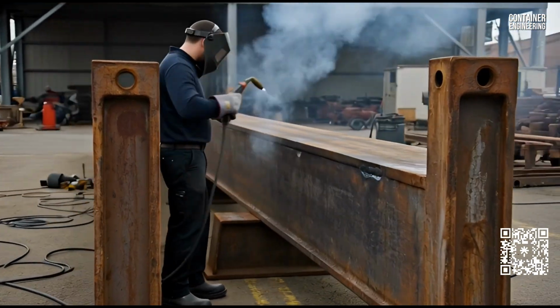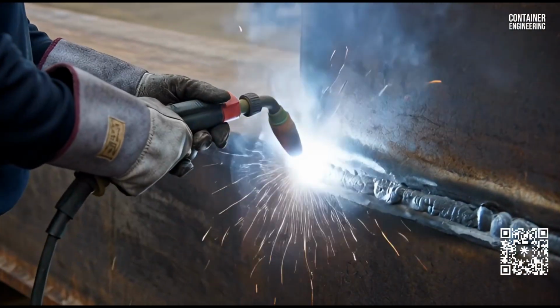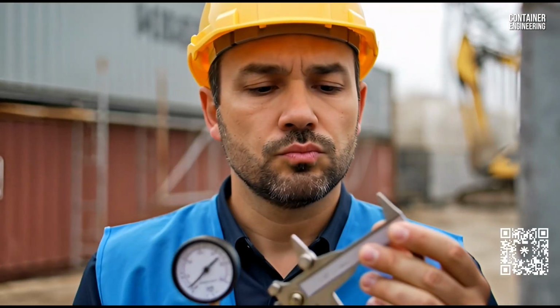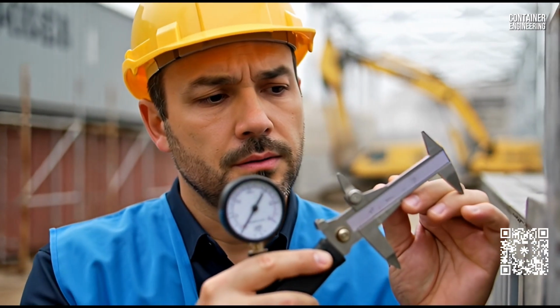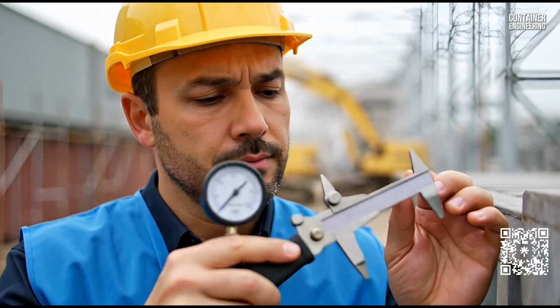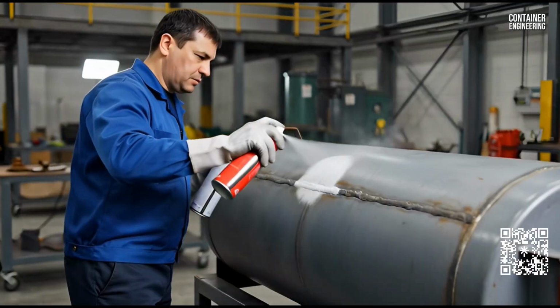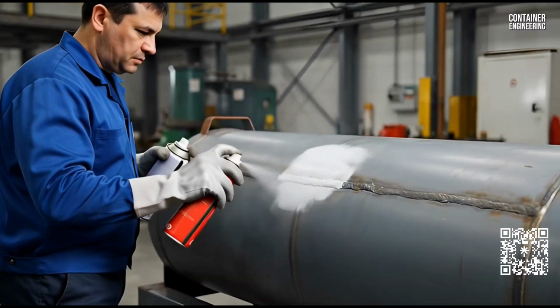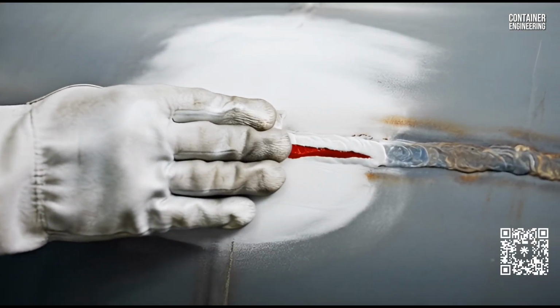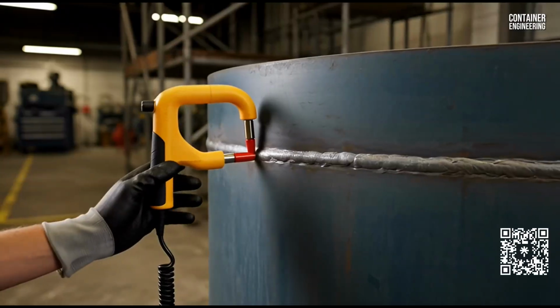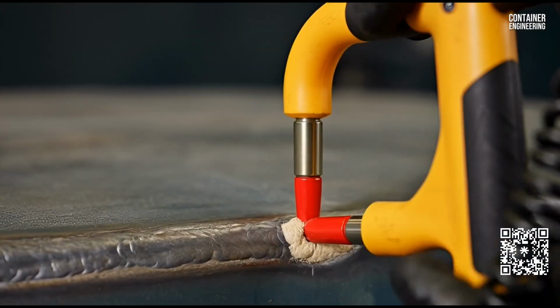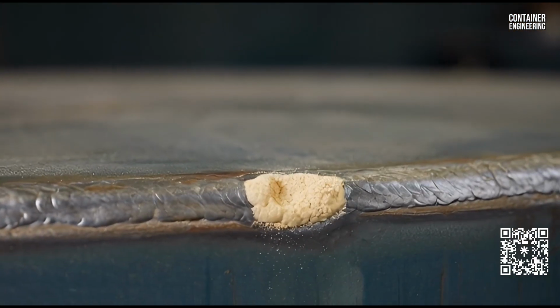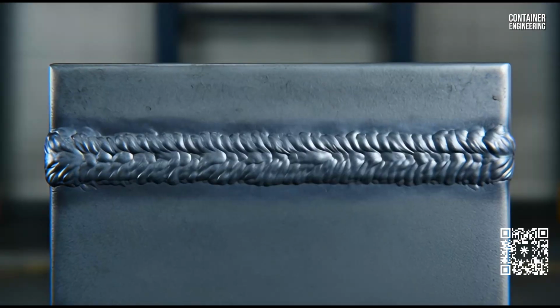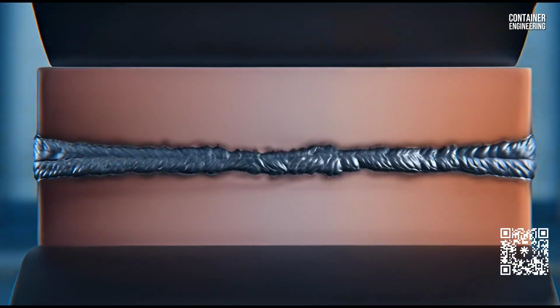A corrugated sidewall with 1.5 millimeter thickness has a section modulus of approximately 0.2 cubic inches per foot of width. That section modulus determines the wall's bending capacity. Reduce the thickness by 25% through corrosion, and you don't reduce capacity by 25%. You reduce it by 43%, because bending capacity is proportional to thickness squared.